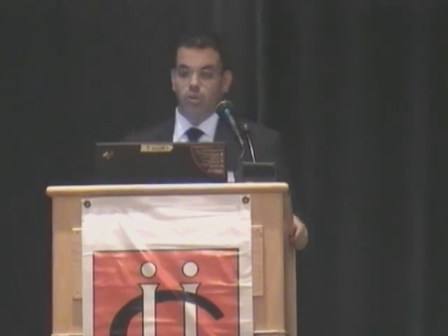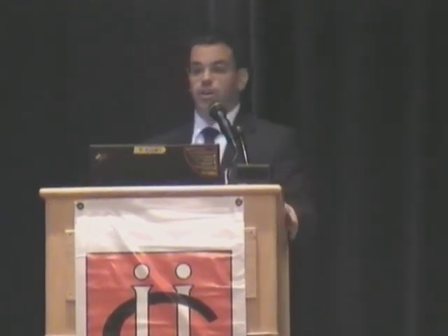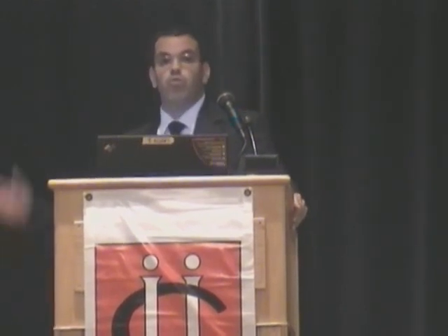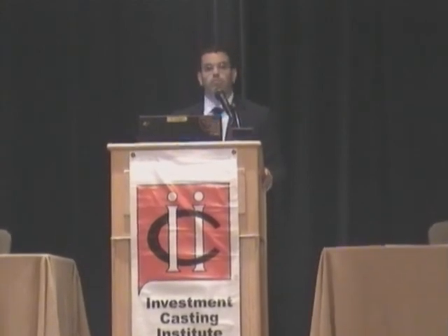So those parts, which are approximately 16 inches long, reducing more than 60% of the gates, meaning you reduce a lot of labor. Putting the gates, gluing the gates, runners, aluminum, cutting them off, and blending them obviously. Capabilities. Well, reduce the setup time and develop a new sample part by 60%. Now we're running one iteration, no gates on the parts. We're seeing where the problems are. Put the gates only where it's needed the most. And we're done with the iteration, and the part works. Reduce the casting defects by 30% just by actually knowing what the problems are.